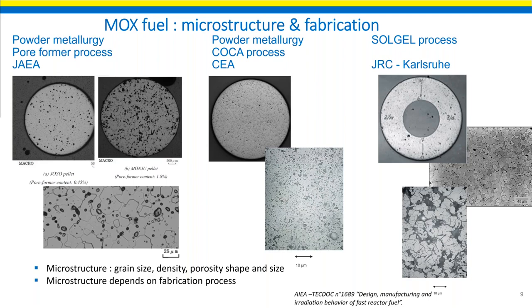A standard MOX fuel has a density of more than 95% and a stoichiometry of around 1.97 to 1.98. So next slide, please.